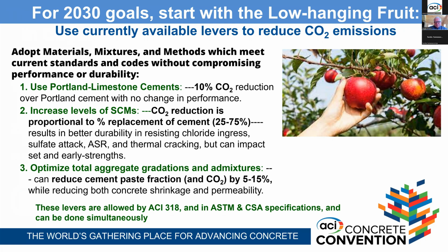So what are the low-hanging fruit? If we're going to go for 2030 goals, which is only 7 years away, we've got to do things now. The things we can do now, the low-hanging fruit that's available in the market and allowed in standards, including the building code: use Portland limestone cement. It offers about a 10% CO2 reduction over straight Portland cement with very little change in performance. I shouldn't say no change in performance. There might be small differences in admixture dosages required, and you have to do optimization, of course, with any new material. Increase the levels of supplementary cementitious materials in the concrete. The proportion of CO2 reduction is proportional to the cement replacement. You're replacing cement clinker by putting SCMs in the mix, as long as you're not increasing the total cementitious materials content.